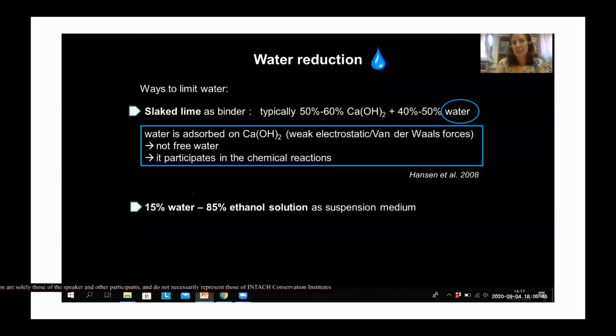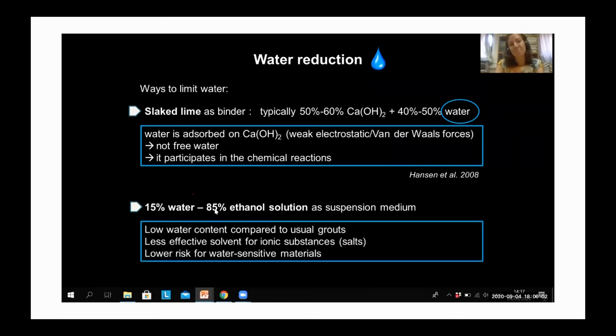And then another way to limit water was the use of a water-ethanol solution as a suspension medium, and in particular 15% water and 85% ethanol, so a really small amount of water. And this, of course, was achieved at the end after a lot of lab testing with different water and ethanol solutions. So if I use this solution, what's the outcome? I have a low water content compared to usual grouts, of course. I have a solution which is less effective in terms of solubilizing salts. And I have a lower risk for water-sensitive materials. But the point is that if I add this solution to the grout, I have very little water, but in the end, the porosity of my grout will still be very, very high. And so it's good for my very porous original materials.